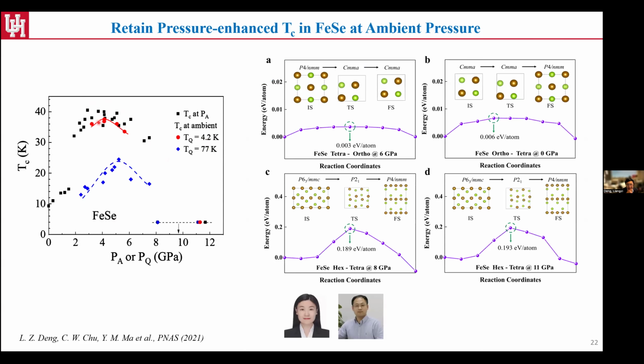So here's a phase diagram summary of all the TCs. All the black spots show the TC under pressure, the blue squares show the TC retained at ambient pressure by quenching at 77 Kelvin, and the red dots show those where we did the pressure quenching at 4.2 Kelvin, and you can see the gap here. So when moving towards the lower quenching temperature, we get much higher TC. As we mentioned, we're really trying to understand a little bit deeper why this could happen.